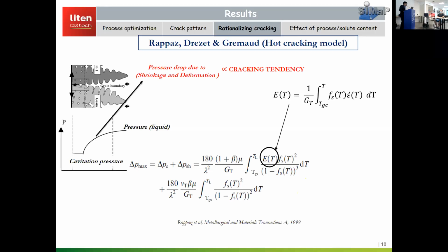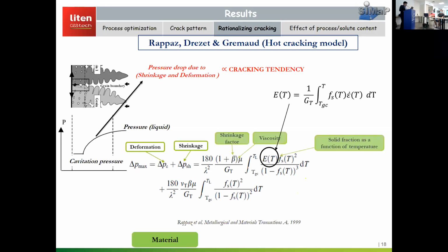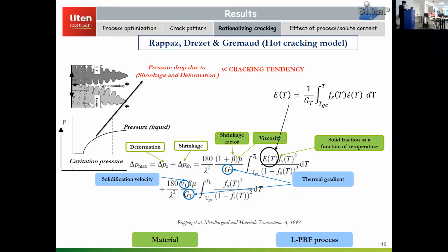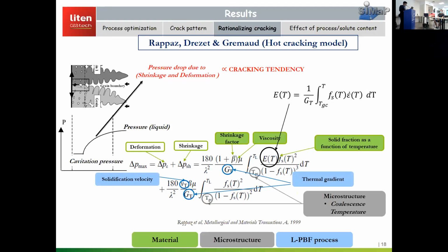So if we look at how we estimate this pressure drop, here it's a big complicated equation, but in a minute I will simplify it for you. It is based on different material parameters like shrinkage factor, viscosity, and the solid fraction as a function of temperature. So these are the material aspects of the model. The process aspects are, for example, the thermal gradients and solidification velocities. There are microstructural aspects, for example, the coalescence temperature, the lower bound of the integral, so at what temperature the dendrites start to coalesce. And there are other factors based on microstructure and processing as well, for example, the primary dendrite arm spacing and the strain rates.